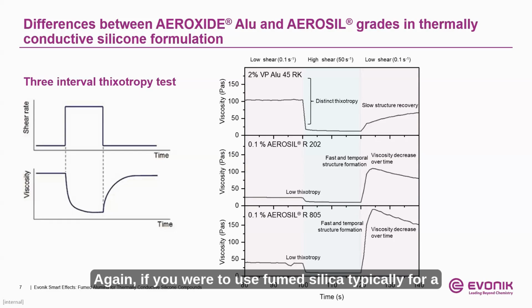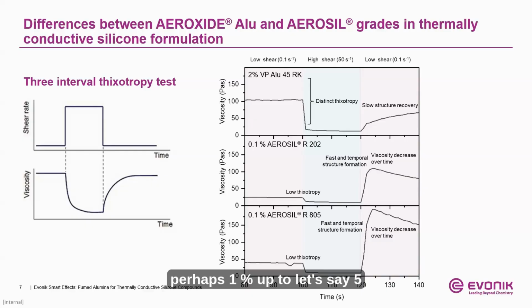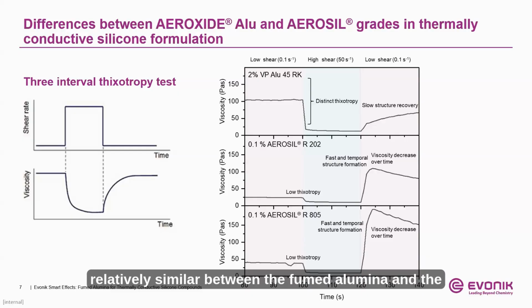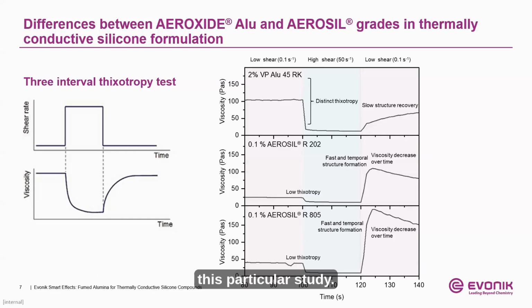Again, if you were to use fumed silica typically for a thickening purpose, for rheological purposes, you would use a much higher concentration here, perhaps 1% up to, let's say, 5%, again, to keep the baseline measurements relatively similar between the fumed alumina and the silica. As a much lower concentration was used in this particular study.